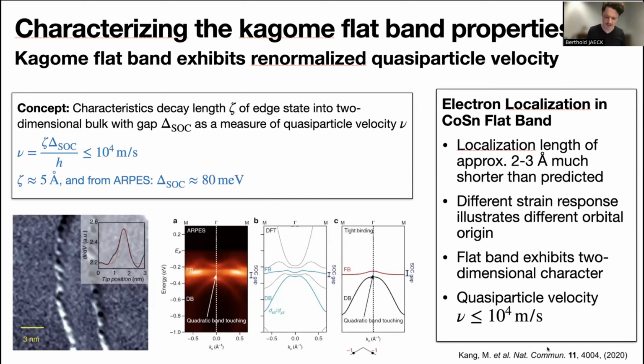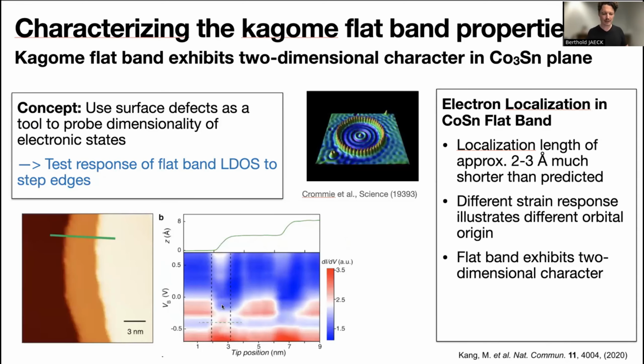Another question we ask ourselves is, how can we further characterize the actual flatness of the band? We know now that the electrons are very localized, at a 2 angstrom localization length. But what does it mean in terms of the band properties? To answer this question, let's go back and look again at one of these step edges. When we look at, for example, such a spectroscopic line cut measurement, we find that the flatband density of states decays towards the edge. What we also find, however, as highlighted here, is that around the flatband energy, we detect an edge state.